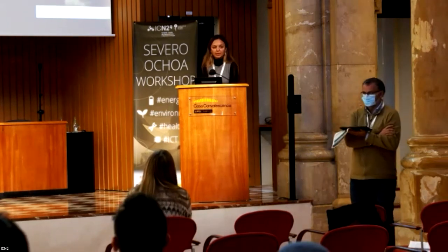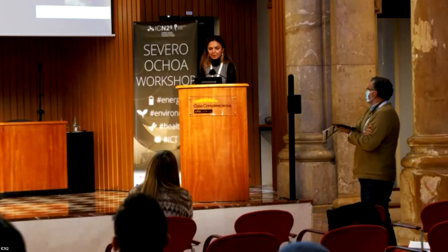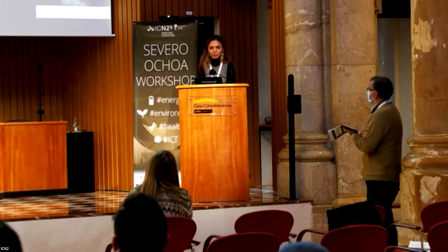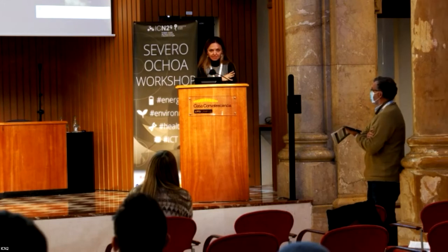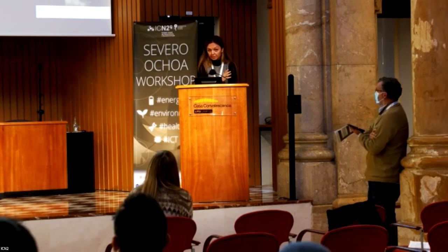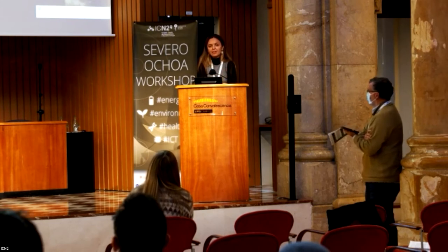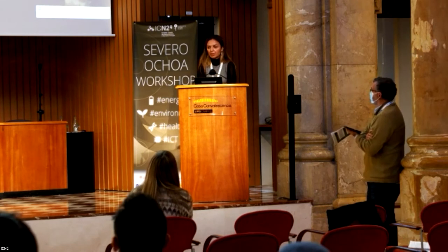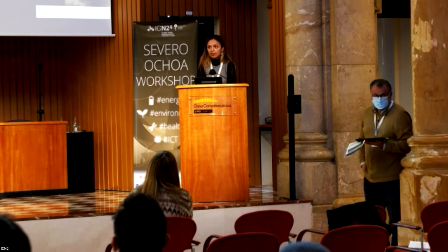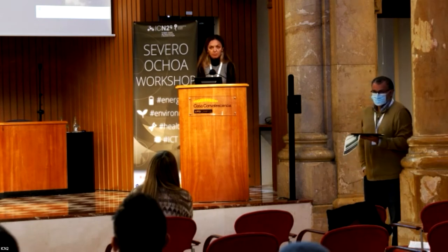Okay, so it is true that it's porous, but it's not microporous. And this would be the problem. For microporous, mesoporous materials, things get inside so much that this is one of the limitations of activated carbon in water treatment. That's why they normally have to burn it if they want to regenerate it. So we really did not have to investigate so far any regeneration strategy because we don't see any passivation. So we always apply current.